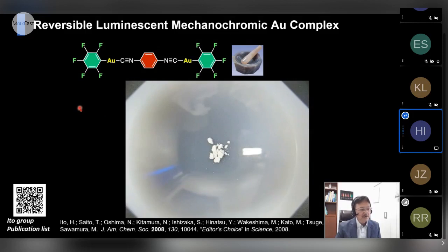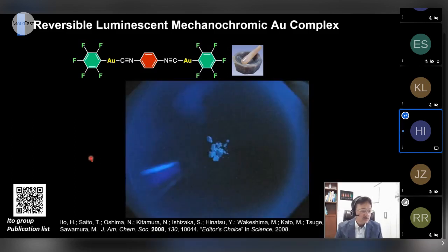I have been studying synthetic chemistry for more than 20 years, but in 2007 we found a very interesting compound during our study of synthetic chemistry. That is this dinuclear gold complex. This is a fairly stable compound. We can handle this compound under air. As you can see, this compound is a white powder under room light, but under UV light illumination, you can see the very blue luminescence of this compound.